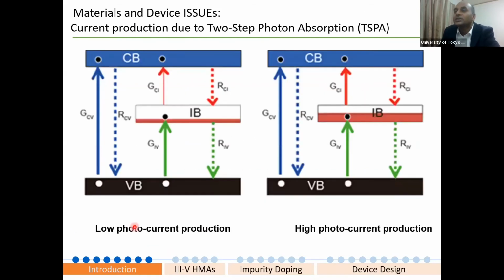Let me just tell you that for the intermediate band solar cell, the very important thing is two-step photon absorption. If you don't have an intermediate band, your infrared light passes through the material. But if you have an intermediate band, then the infrared light can be absorbed by the intermediate band, and two-photon absorption can give you excitation from the valence band to the conduction band. But your Fermi level should be inside the intermediate band. If you have a well optimized Fermi level in the intermediate band, you see very high absorption of the electron, and you can see two-step photon absorption. This is just a schematic picture, and in this case we can get high photocurrent production due to infrared light.